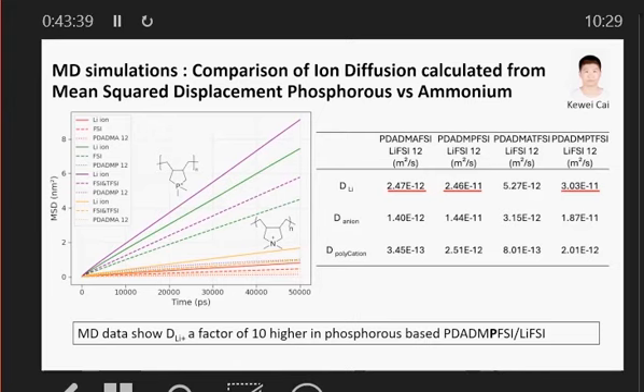But what's really interesting is that we're seeing a significant, almost a factor of 10, not quite. Here we go. The diffusion coefficient of the DADMA is 10 to the minus 12. The phosphonium equivalent is 10 to the minus 11, an order of magnitude higher diffusivity. Now, will this correlate in reality? We'll show in a moment. And it does depend on whether it's TFSI or FSI, homoanions or mixed anions in the model. So that was interesting. That's promising, right? Phosphonium may actually give us better performance if we can make it at a reasonable cost and reasonably more easily.